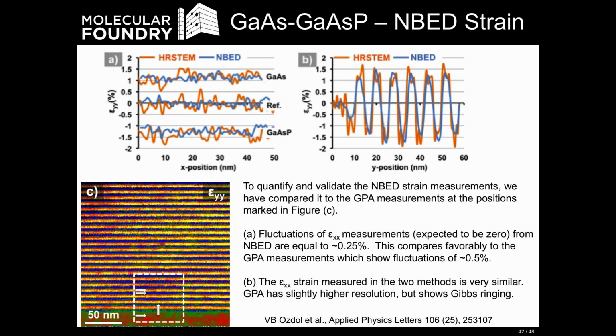The NBED has one minor limitation, and that's there's a sort of finite size to our probe. Our probe is somewhere around a nanometer, and so you get a little bit of blurring between the adjacent layers because the sample is fairly thick here. But overall, I think it's a pretty good trade-off because it doesn't have the noise of the HR STEM scan. So each individual maxima and minima here is usually monotonic. It doesn't oscillate up and down inside the layer. And then, like I said, the other major advantage is the field of view is more or less unlimited. We only have to sample our experiment here. We only have to put our probe positions finely enough to see all of the layers in the multi-layer stack. That's our only limitation here.